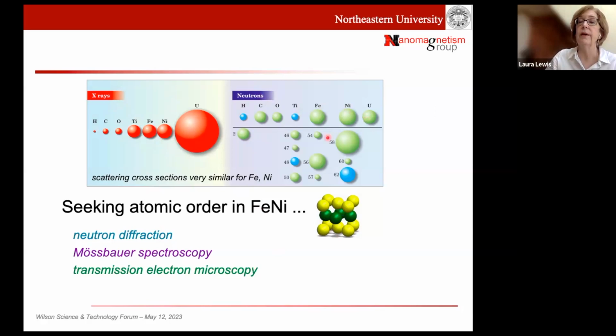I can't tell the order, but nature gave us something very unusual. Nature gave us nickel 62. It is an isotope of nickel that has what we call a negative scattering cross-section. I don't know quite what that means, but it means now that these guys are so different that you will be able to see the superlattice very, very, very easily. So we were able, with the help of Northeastern, to purchase nickel 62. You might be surprised, or maybe not, that a gram of nickel 62 costs $10,000. So these are very precious samples.